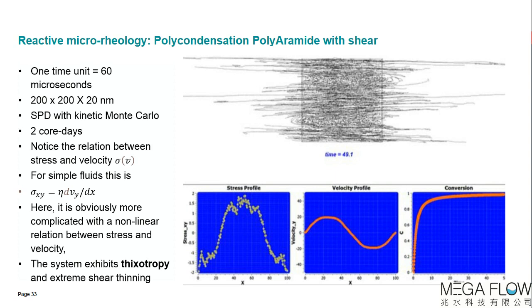So for a simple liquid, the constitutive equation is simply Newtonian, this viscosity here. And for these materials that we have, of course, it's not true. So here, the x-axis, we forgot to put this in on the picture here. The x-axis is in that direction. So what you see here, x is in that direction, and what we do while the reaction is going on, you will see this in the next slide on the video. While the reaction is going on, there is a body force like this, like a sinus, which pushes the liquid in that direction here, and here in that direction. And while this is going on, the reaction is going on, the conversion is going on, and we measure instantaneously the stress profile in that direction and the velocity profile.